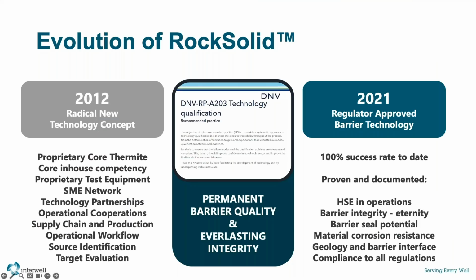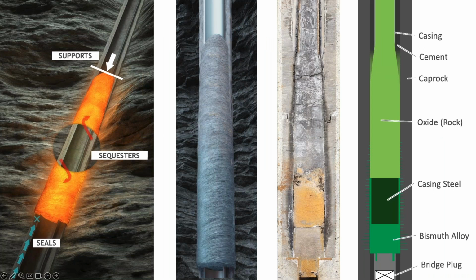During deployment of Rock Solid, once it's at setting depth, the reaction melting process begins. Once the melt is solidified, the resulting barrier is shown in the picture in the middle of the screen. That gray glob, if you will, is another still image from the animation. To the right of that is an actual sample of a full-scale test that's been cut open, so we're looking at 180 degrees of that barrier itself.